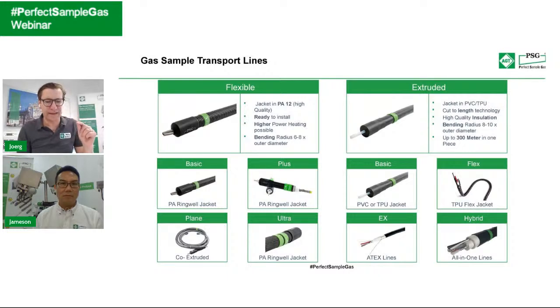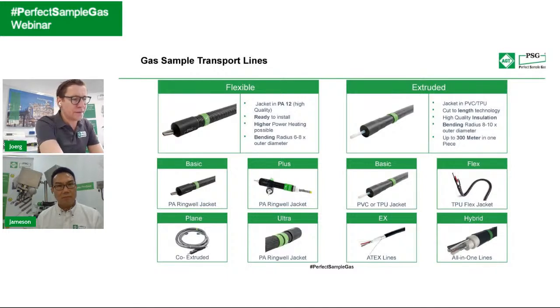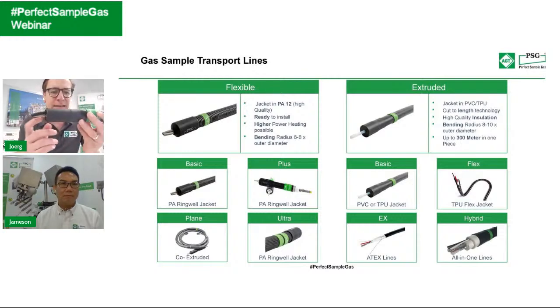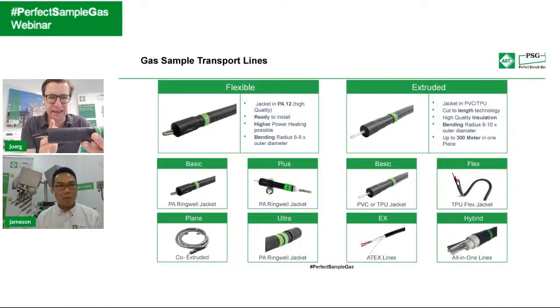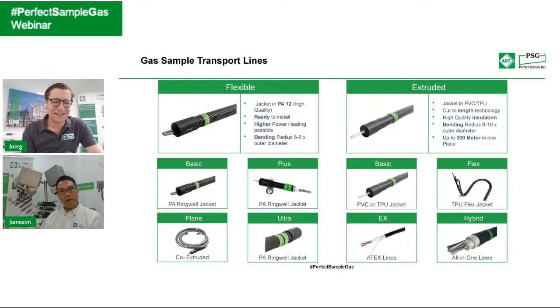It's very often the interfaces between the different components with the heated sample line which can cause problems, especially in the field of condensation. Therefore, if you look at the heated sample line manufactured by us, and this is just an example, even if you buy from other suppliers, please make sure that the heating goes all the way up to the end of the heated sample line. If the heating cable ends somewhere at the end of the cap, maybe somewhere here, people sometimes underestimate how fast gas is cooling down. The heat capacity of gas is so low, so the temperature drop will be immediate, especially with high acid dew points.